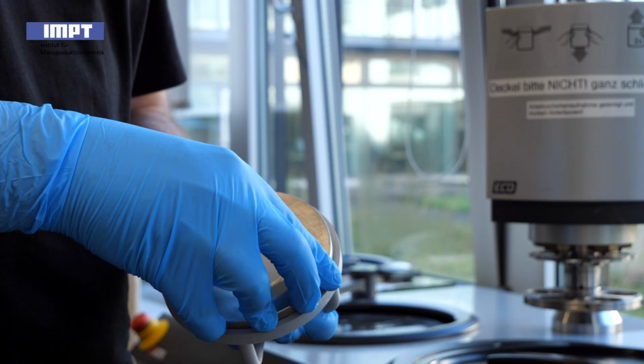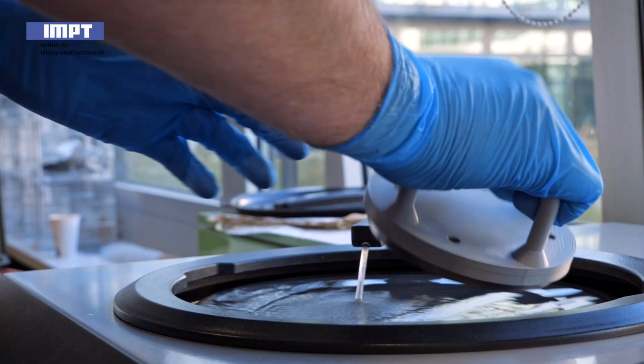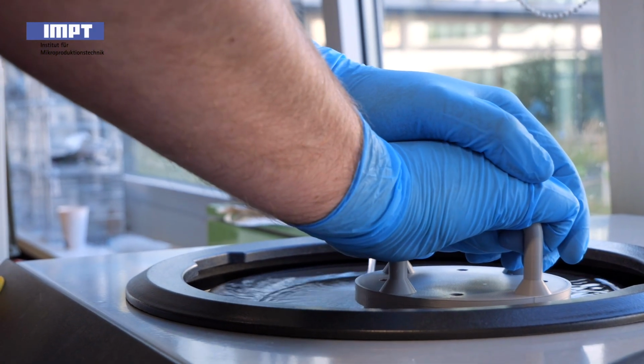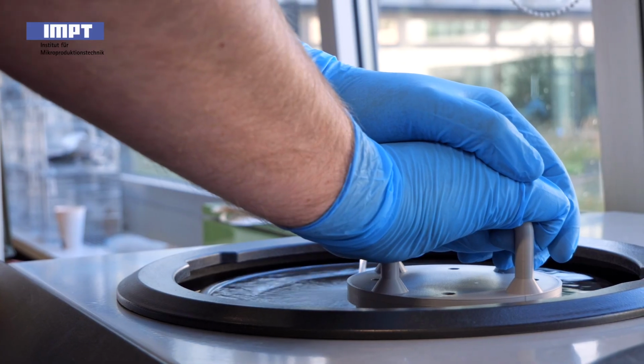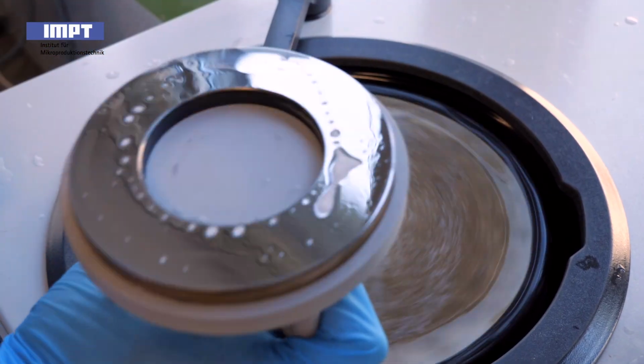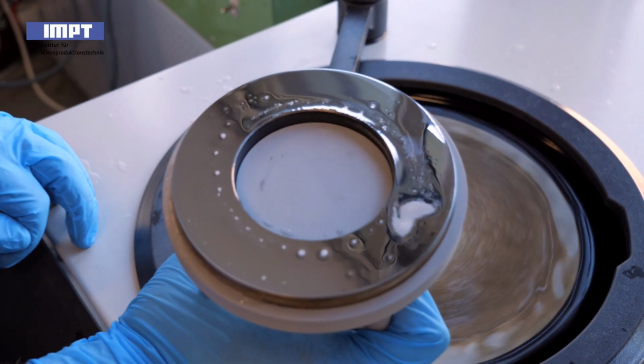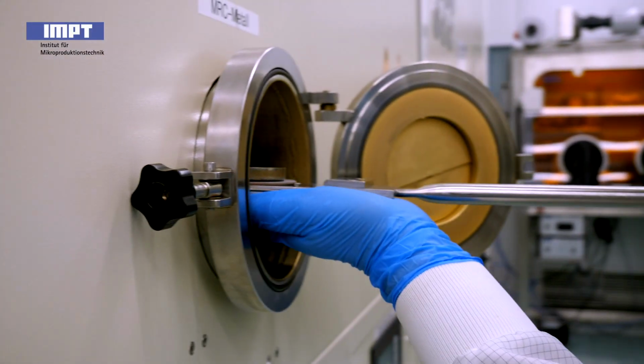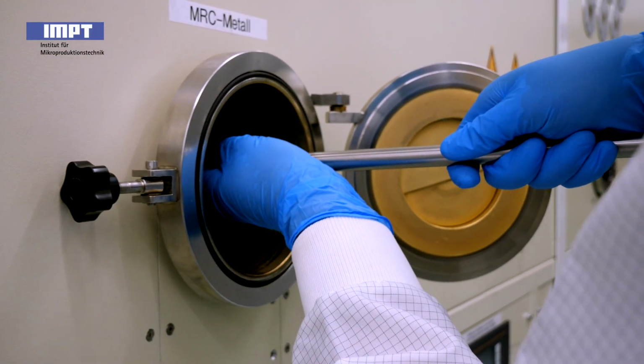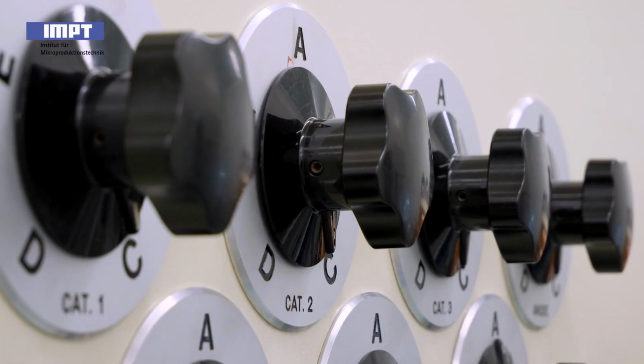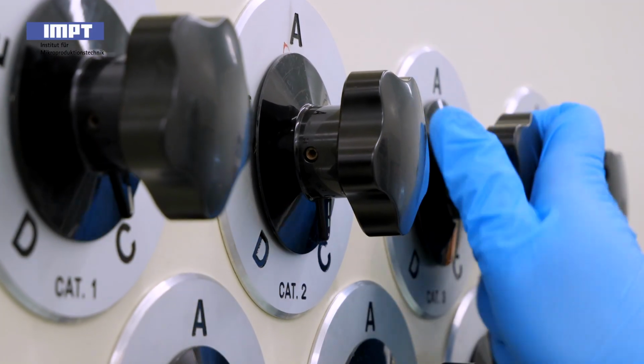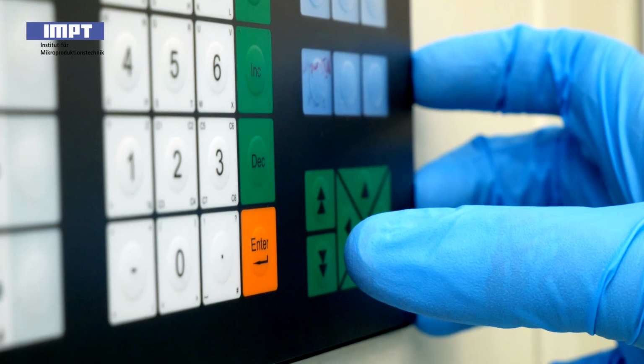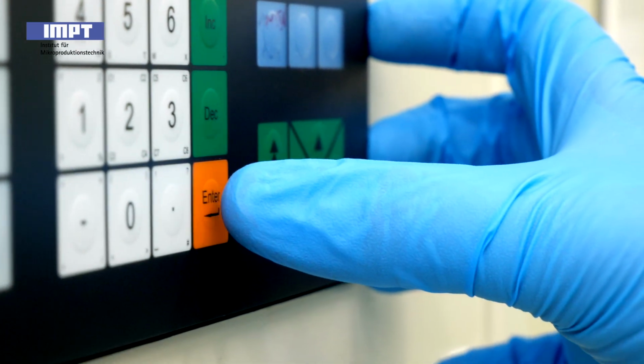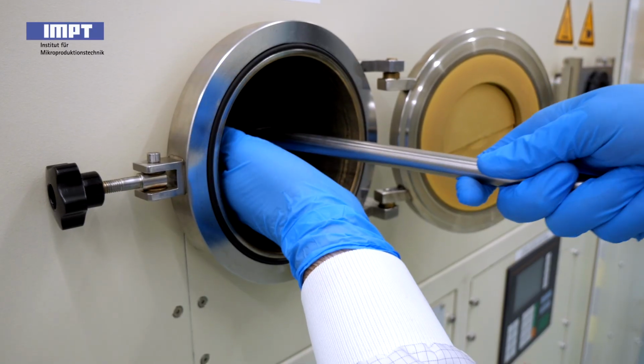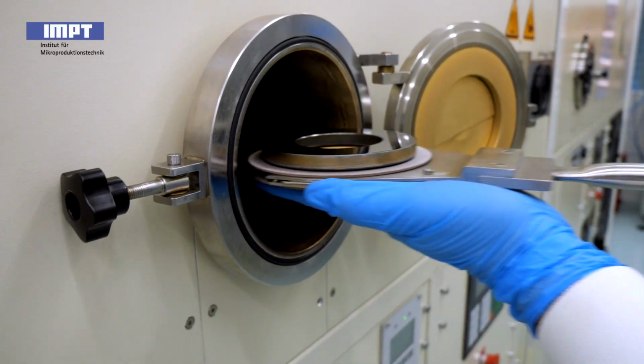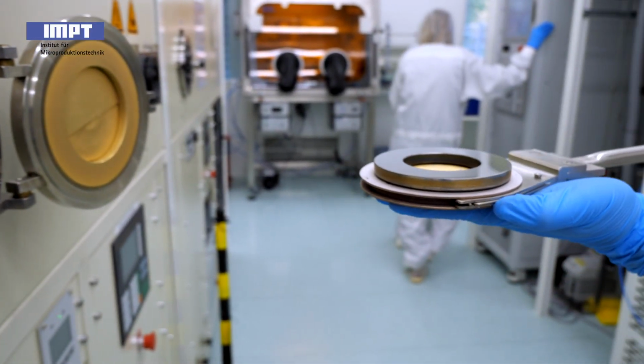At the beginning, the thrust bearing washer, our substrate, is polished using a grinding and polishing machine to create an absolutely smooth surface with low roughness values for sensor deposition. Next, the sensor production begins in our cleanroom using sputtering processes. First, a transparent insulation layer of aluminum oxide is deposited over the entire surface of the bearing washer. This ensures that the subsequent sensor layers are separated from the bearing washer by a non-conductive film.